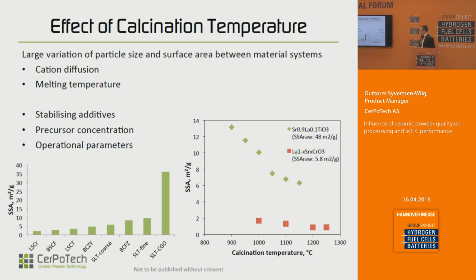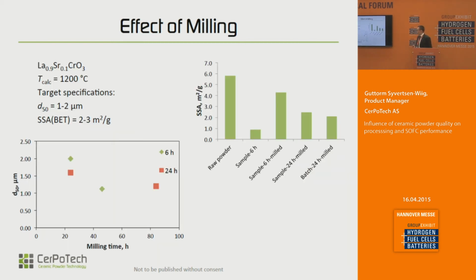So if you want a surface area of, say, 10, then we need to go to 950 degrees or so for the strontium titanate to achieve this. Also we can use milling of these hollow spheres to tune both surface area and particle size.